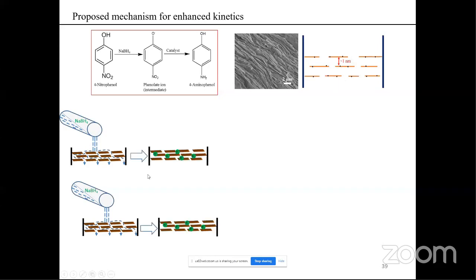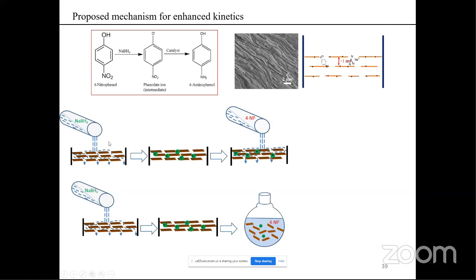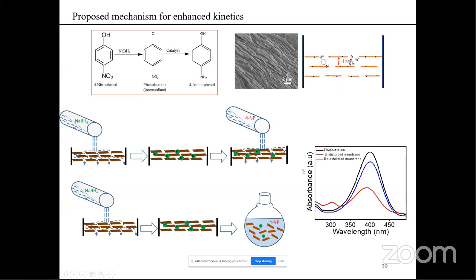To confirm this, what we have done, we have taken two membranes, and in both cases, without nitrophenol, we just put our sodium borohydride. And in one case, after putting the sodium borohydride, we put our nitrophenol reagent, and we can see the reaction takes place when we add both compounds separately. But if we break the membrane after putting the sodium borohydride and allow all the hydrogen ions to go away, then the reaction did not take place.